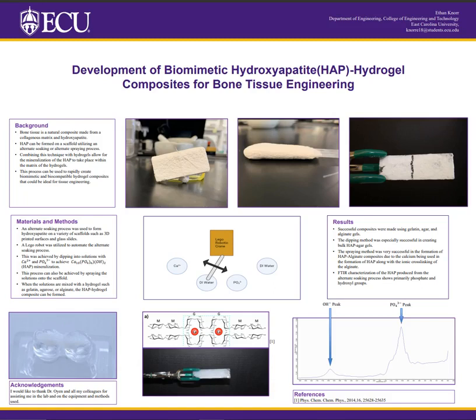For the materials and methods used in this project, the alternate soaking process was where it all started. This dips the scaffold into calcium and phosphate solutions for a minute and then alternately dips them in distilled water for a 15-second rinse. To automate this process, a Lego robotic crane was constructed and programmed to dip the scaffolds at the right time for multiple rounds. For thin samples, roughly 25 dips were used. For bulk samples, that increased to about 100 dips. The figure in the middle shows a general schematic of the setup I was using.